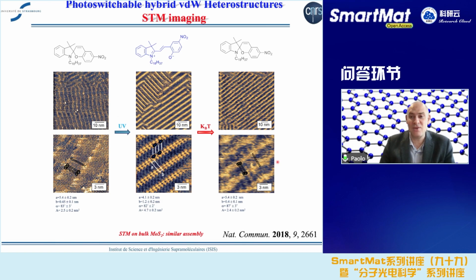And this takes advantage of the high affinity of molecules for physisorption on the basal plane. Now, the only weakness you might have when you play with graphene with respect to graphite is that graphene you typically produce by CVD, and then you have to transfer it onto silicon dioxide. And so sometimes it's not super flat as, let's say, bulk graphite that you peeled with Scotch tape. So there might be a problem of roughness associated with the non-perfect transfer approach.